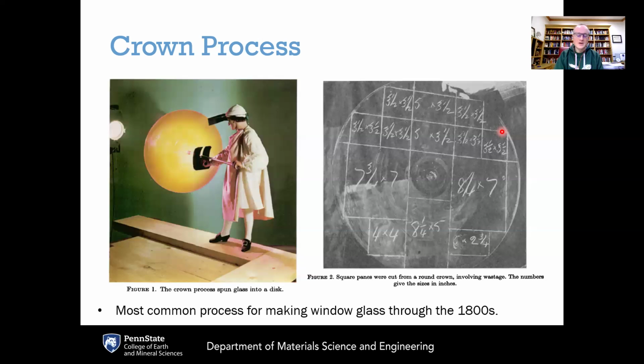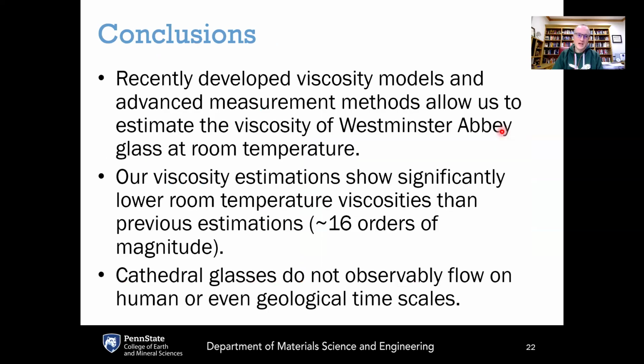And so the cathedral glasses are not flowing on a time scale of hundreds of years. It would take longer than the age of the Earth to really have any observable flow. And the reason for this thickness non-uniformity is because of the process that was used back in medieval times. So to conclude, recently developed viscosity models and advanced measurement methods have enabled us to give a more accurate estimate of the viscosity of medieval glass at room temperature, even though those predictions are about 16 orders of magnitude lower compared to previous estimates. The viscosity is still too high to observe flow.